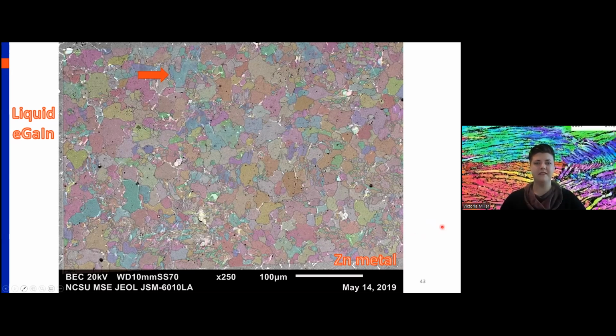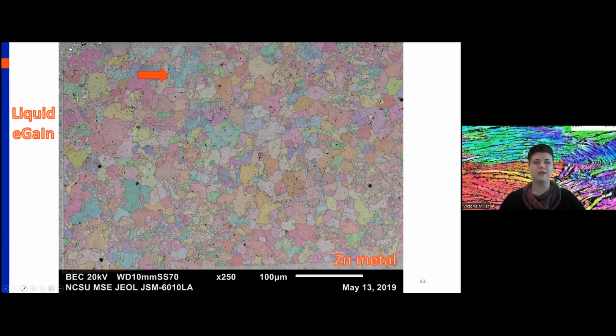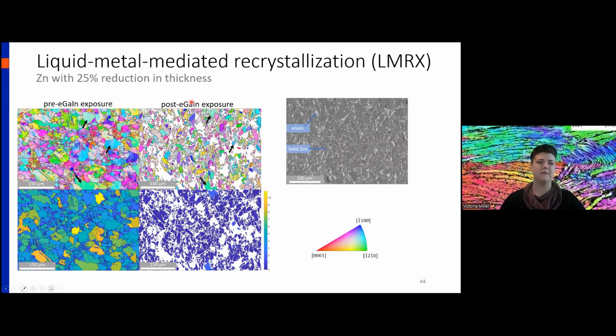And I'll let this play again. We looked at the microstructure pre and post exposure to eutectic gallium indium. Pre-eGaIn exposure, you have a lot of relatively coarse grains that have a lot of internal strain. After eGaIn exposure, you get a lot of very fine grains, none of which have significant internal misorientation. And you can see the amount of internal misorientation on these grain orientation spread maps. You'll note that you do get much poorer indexing in the liquid infiltrated specimen because the liquid fraction of the material no longer diffracts.